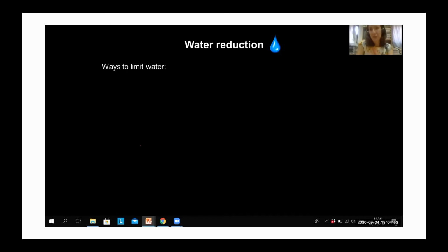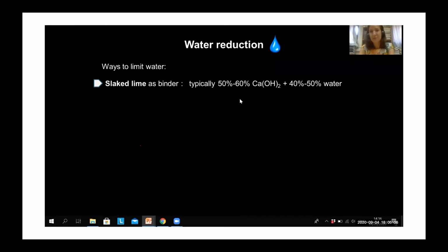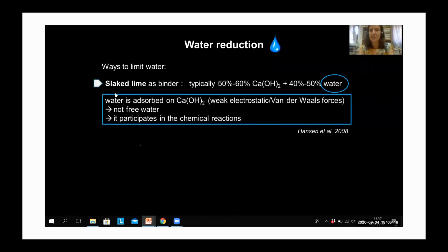So, ways to limit water we used. First of all, slaked lime as binder was used. So we're talking about calcium hydroxide, but slaked lime is basically a paste composed of more or less half calcium hydroxide and half water. So we have water here. But what's the good thing about this? That water is adsorbed on the particles of calcium hydroxide, so it's bound through weak electrostatic van der Waals forces. So it's not free water. It's not just the water we add to the grout, which then diffuses through the porosity very easily. It's weakly bound, but still it can participate in the chemical reactions.